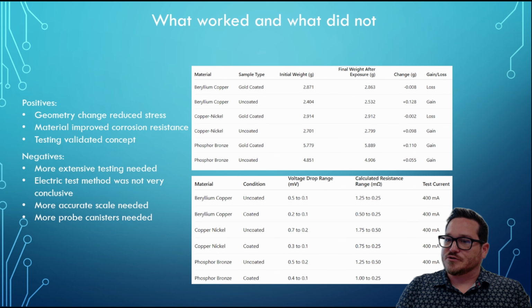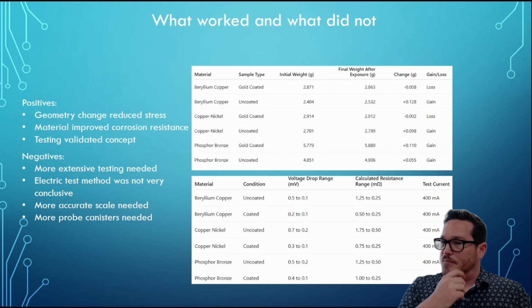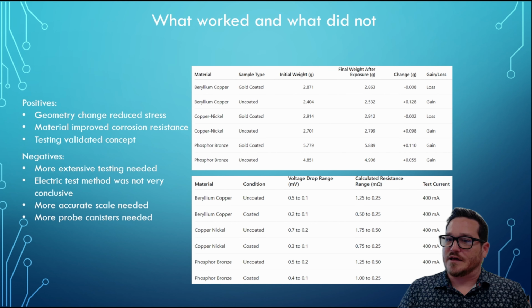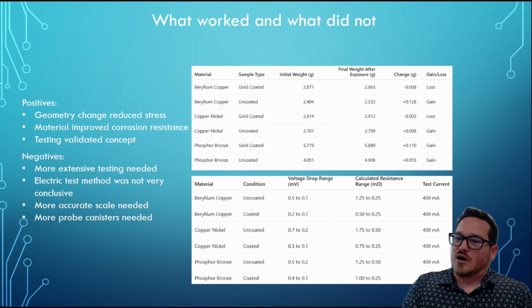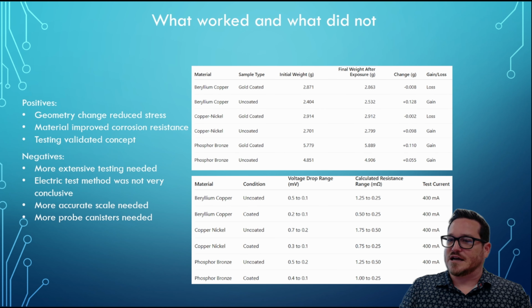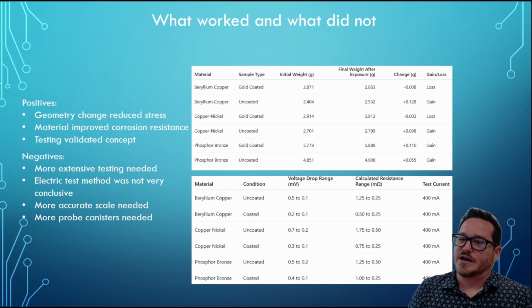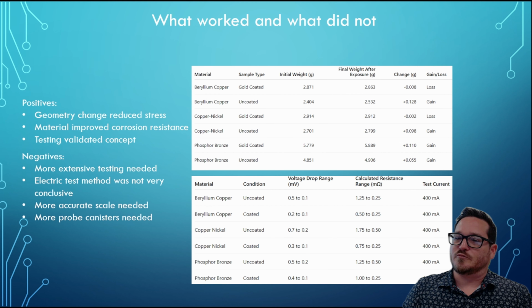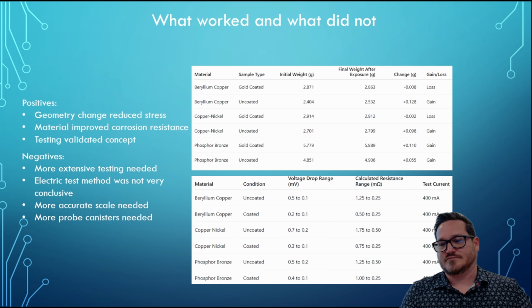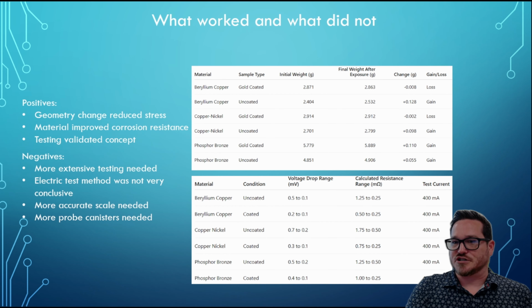The weight readings were also a bit unreliable. Some metals showed a weight loss while some showed weight gain. This made it difficult to make reliable conclusions. The scale I used was in the chemistry lab and only measured to the milligram. I think a more accurate scale, hopefully down to the microgram, would yield more conclusive results. Also, to truly test stress on the contact pins, I would need a new probe canister for every test cycle, but I only had the one, so it would be hard to justify doing 3,000 test canisters and not actually using them.